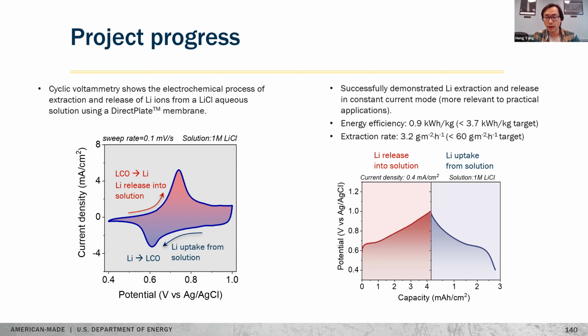At the moment, with this applied current, our extraction rate is 3.2 grams per meter square per hour, which is below our target. But this is because we intentionally applied a small current to utilize the full range of lithium storage capacity in the membrane. In practice, we can limit our extent of reaction, and as the CV curve shows, we can go at least 10 times higher current for this particular material, and further material improvement can lead to higher extraction rate.